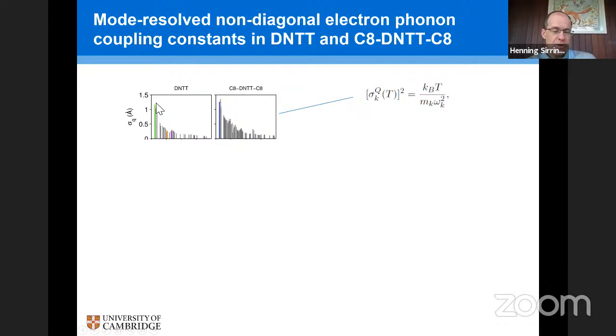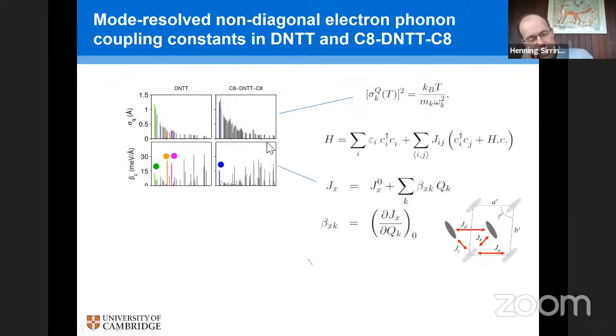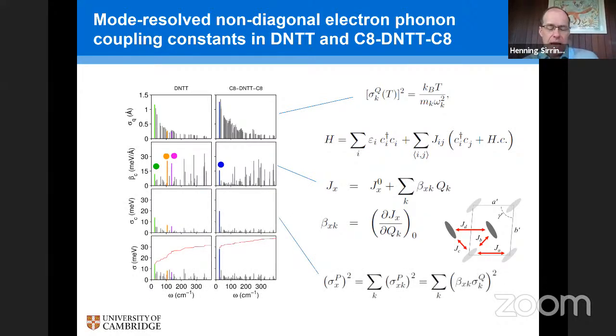You can see that the lowest frequency modes have the highest amplitudes, and then the amplitude decreases to higher frequencies. And then for each of these modes, we can analyze the electron-phonon coupling. The electron-phonon coupling is essentially the derivative of the transfer integrals with the normal mode coordinate. It tells you how much the transfer integral in a particular direction is modulated by that particular normal mode. And then the thermal disorder that's created as a result, the thermal disorder in the transfer integral in particular, is in a sense the product of electron-phonon coupling times amplitude. And you can see this here at the bottom in a cumulative plot where this is the total thermal disorder that's present in this system, built up as we go from low frequency to high frequency and take into account the contributions of these individual modes.